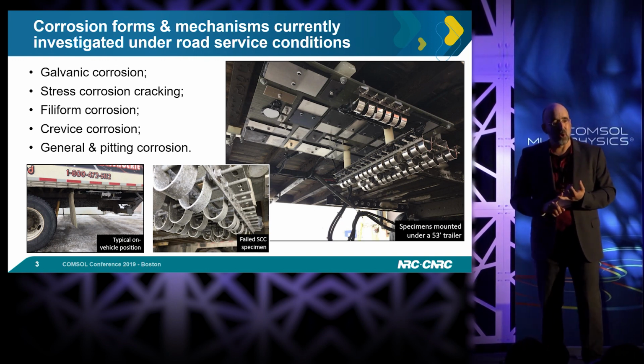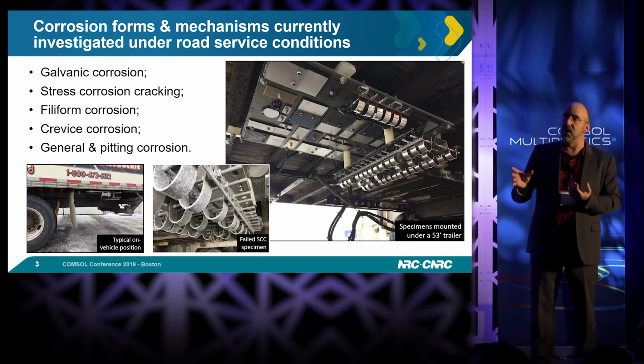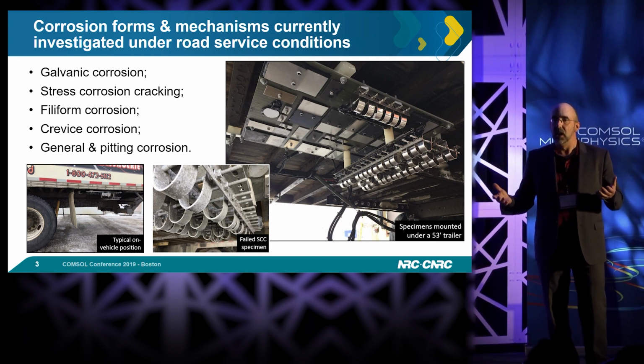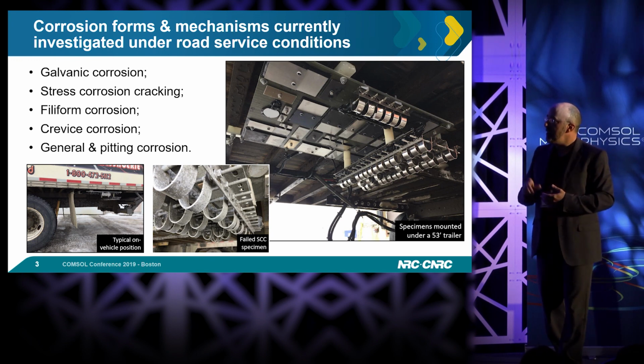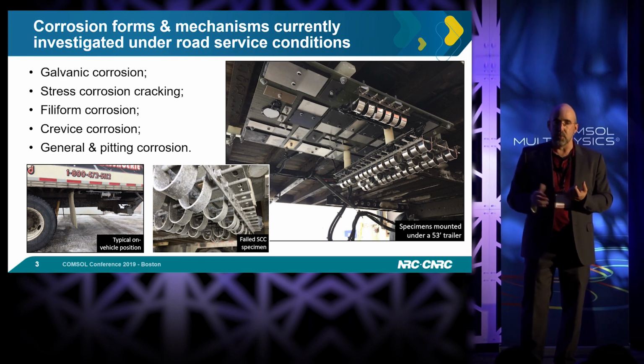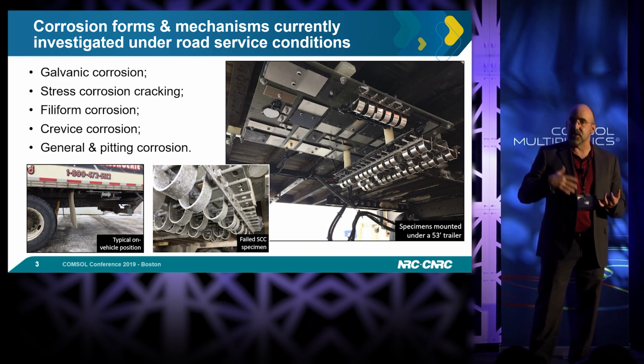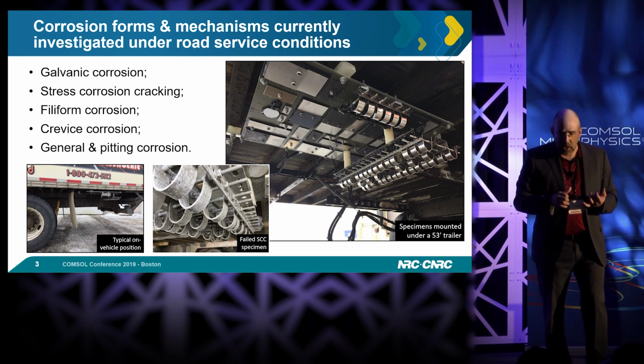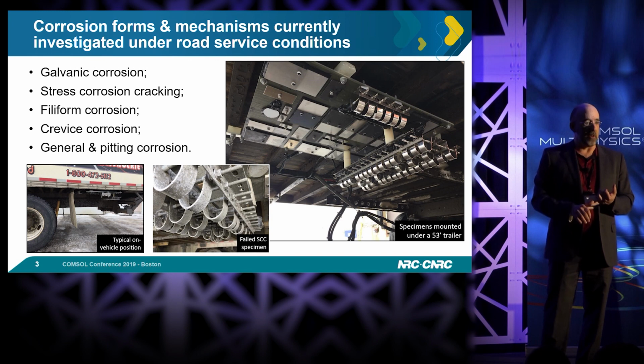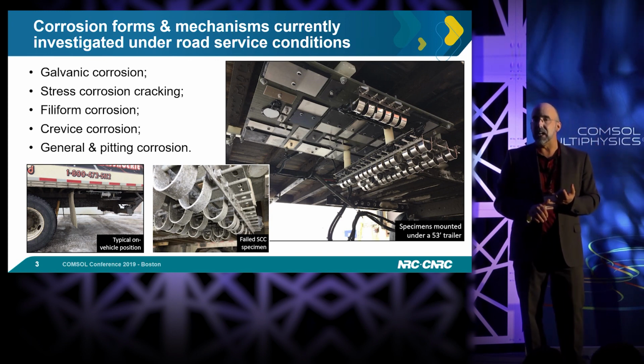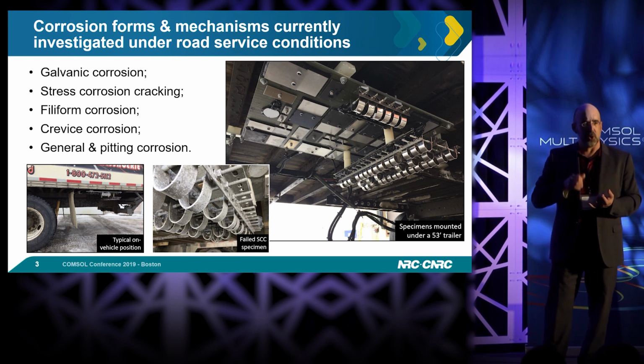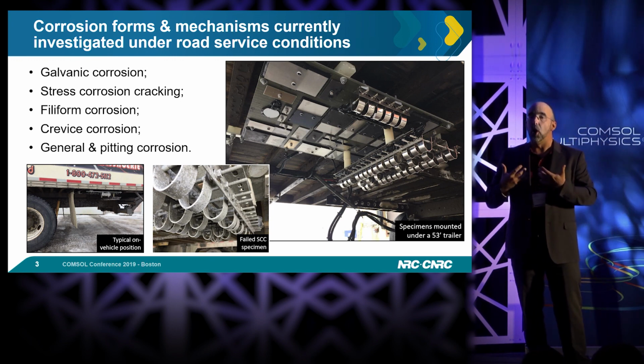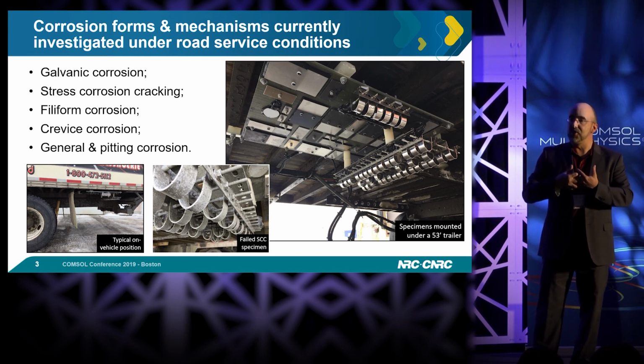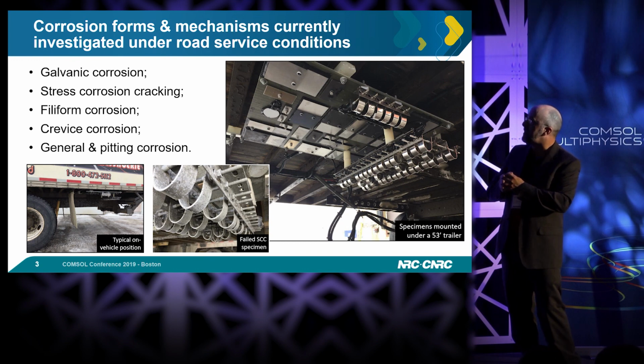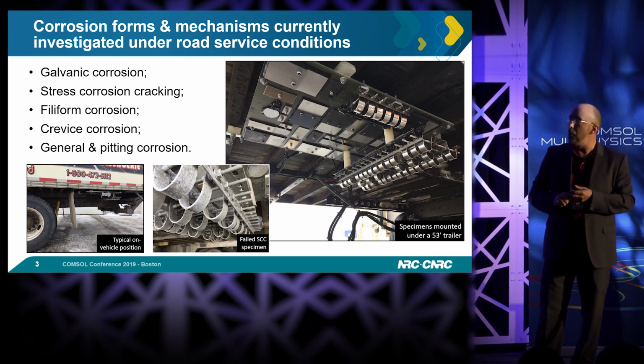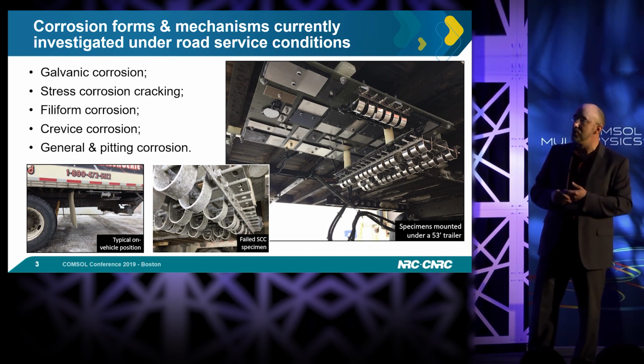Stress corrosion cracking. At the time that steel was the only material to build cars, it was not a big issue. But now we are talking about lightweighting, so we bring materials such as high-strength aluminum alloys, the 7000 series, among others. We combine to this carbon fiber reinforced polymers. The carbon fiber is a good cathode material that will induce corrosion to steel, to aluminum. So we are now combining all those materials, and that was not the case 10 years ago. Now that's the reality.